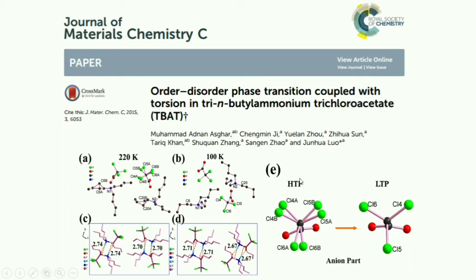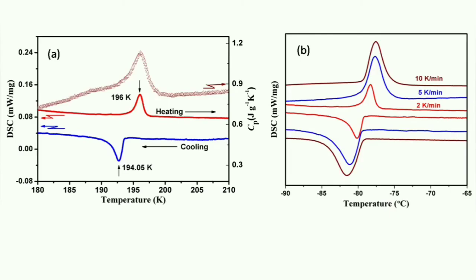So the word order-disorder is actually due to the LTP, which means low temperature phase, and HTP, which means high temperature phase. How would we know this is LTP and HTP? Because when we subjected this material to differential scanning calorimetry, which is named DSC internationally, we observed heat anomalies in the temperature region of 194 to 196 Kelvin. Here in this picture we can clearly observe heat anomalies while heating and cooling at 196 and 194.05 Kelvin respectively.